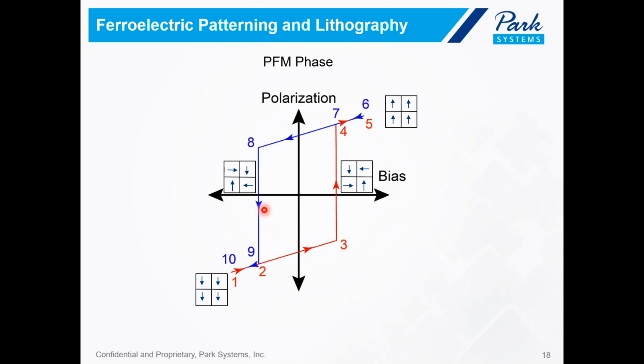So here is an example of how a ferroelectric material will behave in response to an applied bias. So we can increase the bias or the voltage above this value to allow for the domains in this case to be directed to point upward like this. Or we can reduce the bias to a voltage that is below this value to achieve a downward electrical polarization. In brief, what we will do is to apply a sufficient positive voltage to allow for one direction of polarization, and then we will pick another region, and we will then orient the electrical polarization in the opposite direction by applying, say, a sufficiently negative bias.